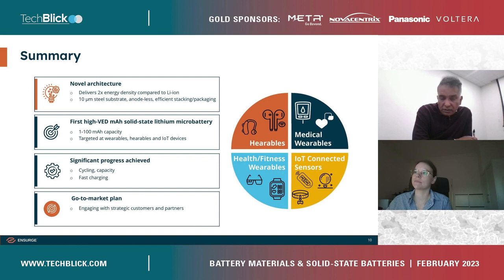It's really the cathode. We use LiCo. We've been open about that. And yes, you can go and operate for limited times to get even higher energy densities, going up to 4.5 volts. But with excessive cycling in that regime, the crystal structure of the cathode at some point will start to collapse and you will lose cycle life.